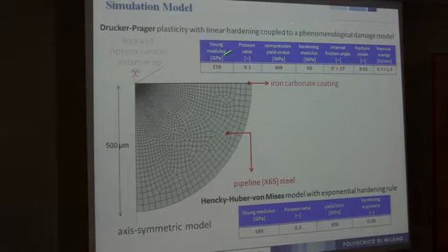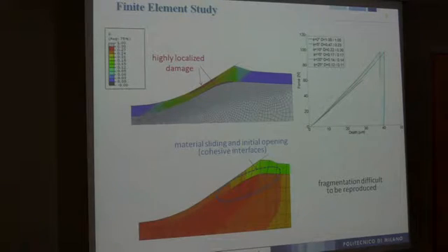the coating. In the initial phase, we are using finite element models. For this coating, which also presents some brittleness, we were using an elastic-plasticity model with a phenomenological model to describe the damaging processes. So what one can see using this kind of analysis is that we can reproduce the main features, for example, what concerns the force displacement depth. Also in this case, the outer curve is the one which concerns the damage model, and then depending on the characteristics of the coating, you can have different responses, similar to the experimental one.